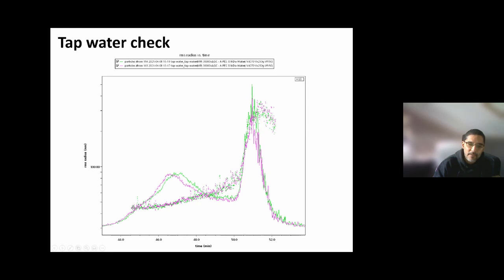If you just look at this line, don't pay attention to the peaks. These peaks are just scattering peaks, but these are the sizes that we detect, which you can see is in the range below 100 nanometers, and you can also see quite a big population of these nanoparticles. And that is just a tap water check, water from our lab.